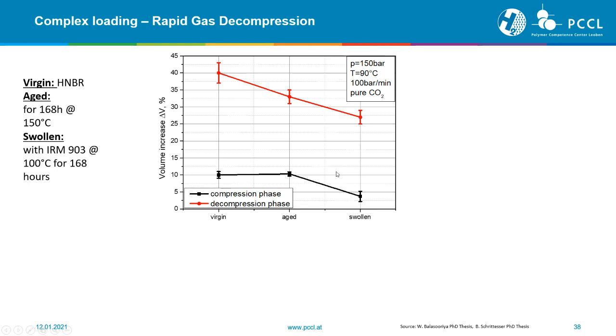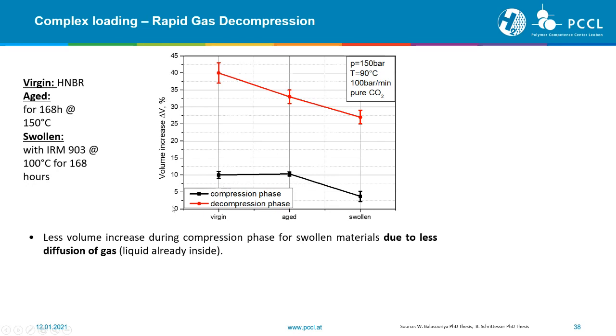Also, these results look in the first way a little bit weird, but when you think a little bit closer about what's happening in the material, then, for example, for the swollen material, we've observed a lower volume increase. This is more or less clear because we've already liquid inside of the material. This means that there is not a big capability of storing gas inside the material because our material is already swollen.